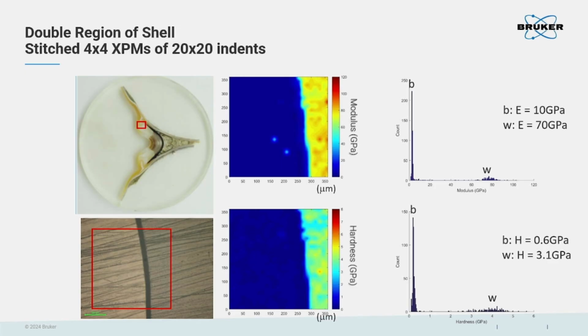So we get the idea of the distribution together with the mean value by looking at the peak value of the histogram. Similarly, we can do the same thing for the hardness. Again, this is the mean value of the hardness on the right-hand side, which is 3.1 gigapascal, which is higher. And on the other hand, for this portion on the left-hand side, the hardness is much lower, only 0.6 gigapascal. So this is a very easy way to understand these two components, especially in this shell structure.